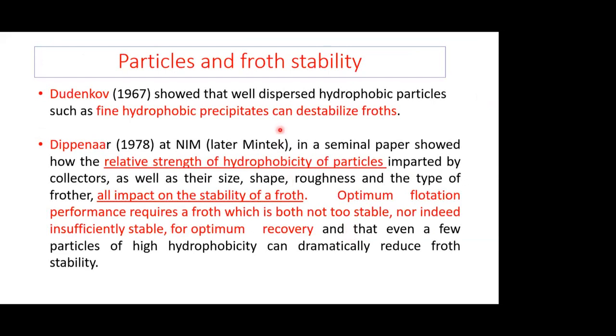Froth stability, again, one of the key aspects of flotation. Dudenkov, way back in the 1960s, showed that well-dispersed hydrophobic particles can destabilize froths. And of course, this led to a lot of work where we know that the hydrophobicity of the particles in the froth phase can stabilize or destabilize the froth. Dippenaar at NIM in the 1970s, in a seminal paper, it's a great paper actually, showed how the relative strength of hydrophobicity of particles all impact on the stability of a froth. Graham Jameson has done a lot of work on this, together with his dear colleague, Seher Ata, and it all comes down to the fact that optimum flotation requires a froth which is both not too stable, nor indeed insufficiently stable. But it goes back to the 1960s and 1970s, this concept.